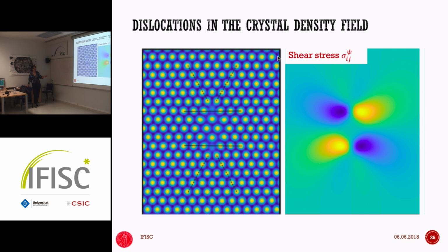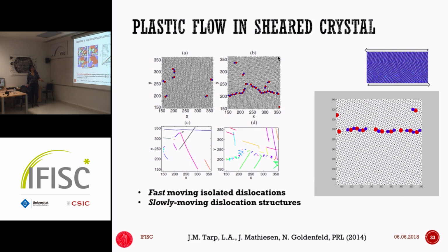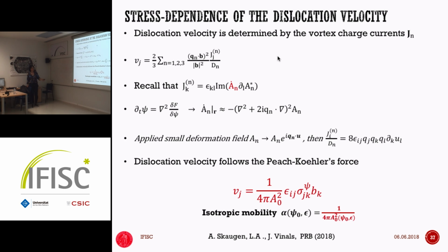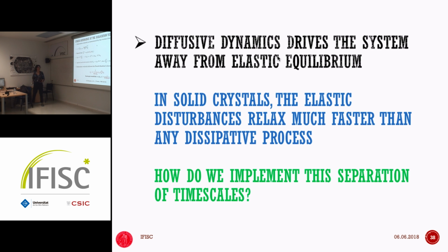But when we are close to the critical point, this is the regime in which the amplitude expansion that we have been using mathematically is strictly valid, then both motions are allowed. And so you could see both the climb and the glide. And in that case, we predict that the mobilities are the same. But in reality, they're not the same. The mobility for the climb motion is very much dependent on the temperature, and it's going to be very much reduced at low temperatures. Of course, analytically, we're in a restrictive regime, but nonetheless, numerically, we still have a reliable way in which we can calculate them, even at deeper quenches. So this formula is not going to be valid everywhere, but the basic formula that we are using, we have shown that it actually works also in lower quenches.